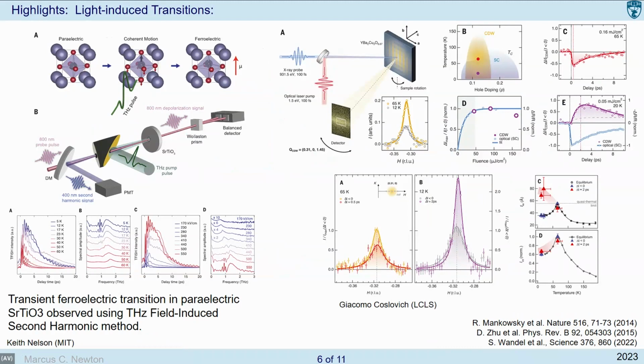Okay, moving on. Here we have an important study with strontium titanate. This is Keith Nelson's study at MIT, and this isn't using an XFEL X-ray probe. In this case, it's using an 800 nanometer probe. But the main point is that it was a very early study, which was able to reveal some interesting properties of this particular material.